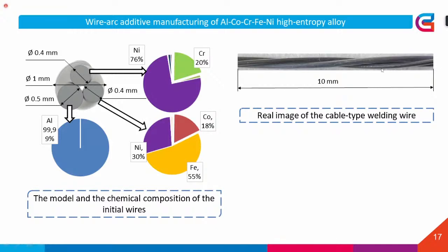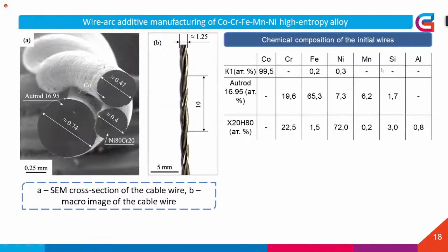The first alloy was received by using aluminium wires and the nickel chrome alloy, and then the wires that include ferrum, nickel, cobalt. So in the left slide, you can see the sizes of the wires. On the right, you can see the real twirled wire, the real image of the welding wire. And the second alloy is shown here. It's cobalt, chrome, ferrum, manganese, nickel, and here we have used this cross section of the cable wire, and the chemical composition of the elements is shown in the table.